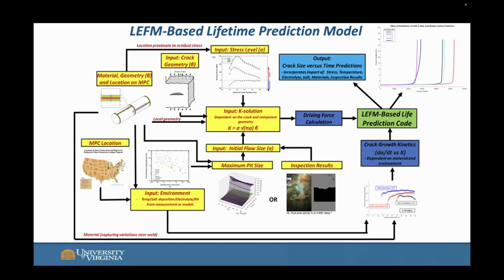This was the model. Basically, we used a bunch of different things. I'm not really going to focus on this for the talk, but the overall goal was you input the stress, you input geometry, flaw sizes from either inspection results, which we've been doing with the Department of Energy, or just maximum pit size models that come from Dr. Kelly's group at UVA. This will then create the driving force. We use da/dt versus K crack growth kinetics. Combined with that driving force, you can get a lifetime prediction, was kind of the goal.